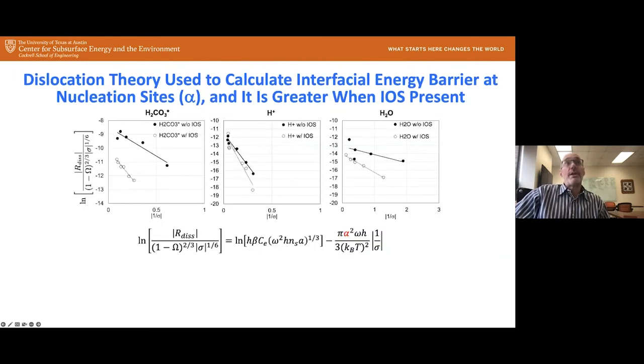So a couple of things we can do. One, we use dislocation theory. This was first laid out very nicely in a PNAS paper by Patricia Dove. And it's basically a kinetic model that uses crystal growth or dissolution theory and the assumption that the dissolution rate is going to be related to basically the number of defect sites, the depth of these defects, and then the step speed and spacing. And she goes through a really nice derivation. And the key parameter that we want to get out is this interfacial energy barrier for dissolution. And you can think of it as like an activation energy barrier.